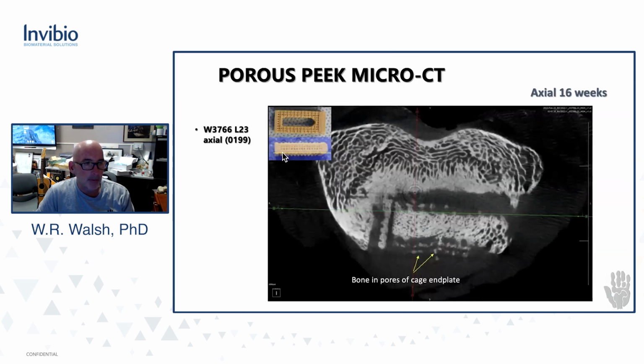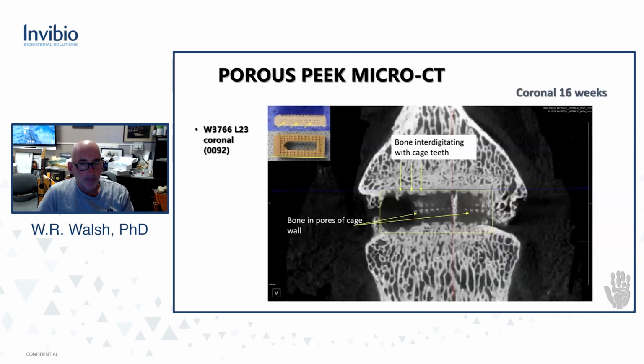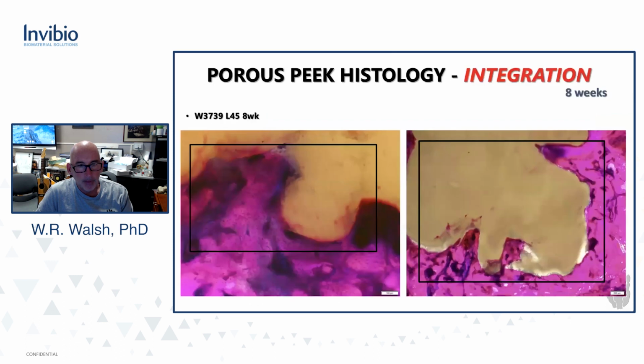And if we cut this now just a little bit deeper into it, we can actually see the bone integrating into the porous domains of the device over here. And you can see more deeper spot welding, and it's actually going through. So it's actually grabbing, the implant and the bone are grabbing each other at multiple spots. And the final slice here is where we're cutting it in the coronal plane. And you can see bone streaming right on the outside of the porous bits of the implant right through here, connecting one vertebral body to the next. And you can see the outline or the silhouette of the cage, but you can see right through it. So you can actually see the bone.